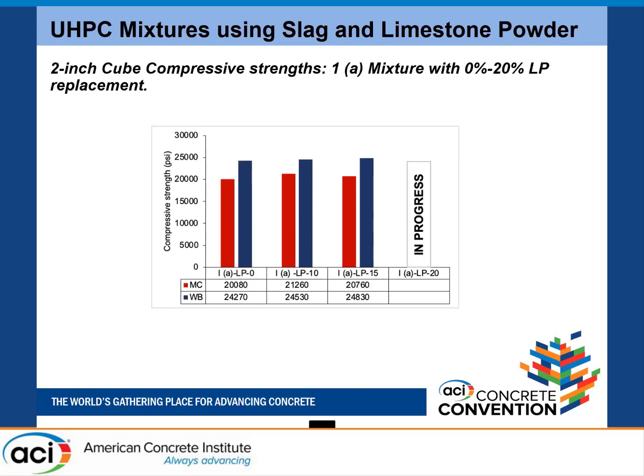where they will be using 1,500 pounds of cement and other cost-expensive materials such as quartz powder, sometimes applying presetting pressures, and expensive facilities may be needed. But this UHPC can be produced with your local materials. It can be mixed on your job sites. You can easily train your workforce for your bridge applications or construction applications to make use of the great benefits of this particular product.